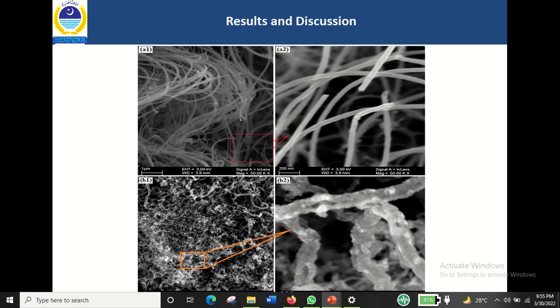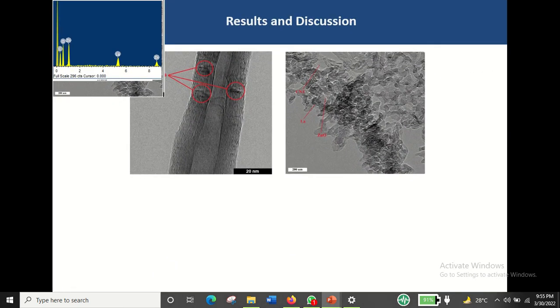It clearly shows that there is a deposition of the zinc oxide and lanthanum on the surface of the carbon nanotubes, confirming the formation of the composite photocatalyst. These are the transmission electron microscopy images of the pure carbon nanotubes on the left hand side, showing some structural defects in the wall which are supportive for the reactivity with the zinc oxide and lanthanum. The right hand side shows the TEM image of the composite photocatalyst, which shows the deposition of the lanthanum and zinc oxide on the carbon nanotube structures.